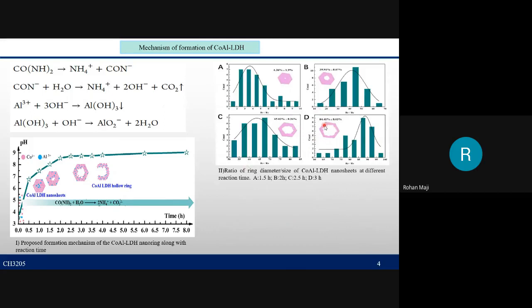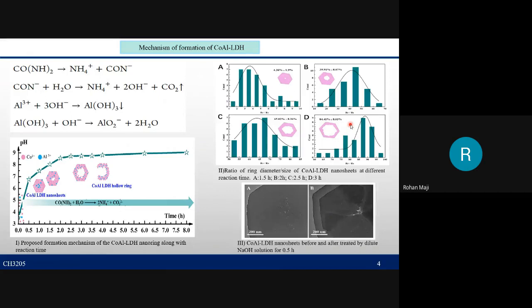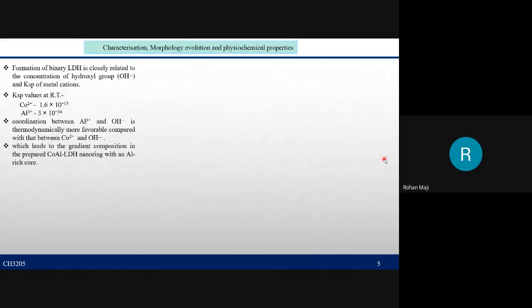Now, a larger change in the diameter of the hollow ring indicates that the dissolution of the cobalt aluminum LDH core is faster than the further epitaxial growth of the LDH. The proposed OH- etching of Al3+ is verified by directly introducing dilute NaOH to the cobalt aluminum nanosheet. So, by now, we have understood that the selective etching by OH- gives our desired nanoring shape.